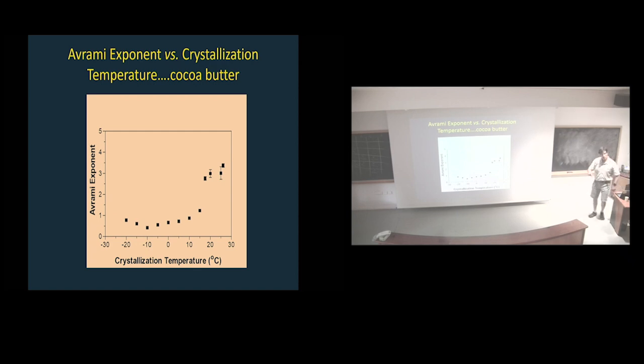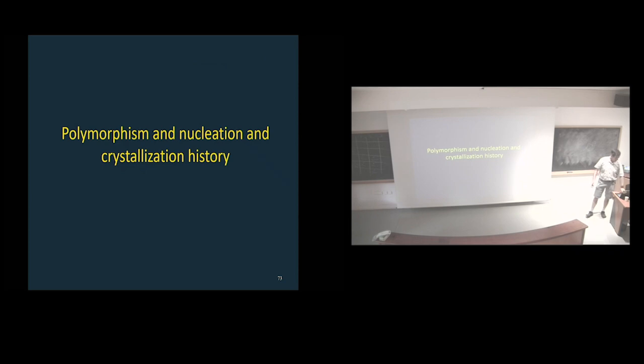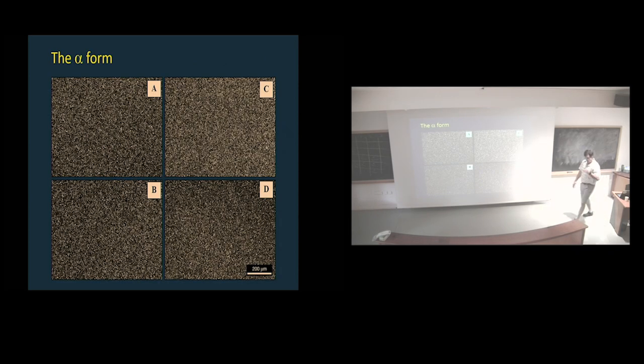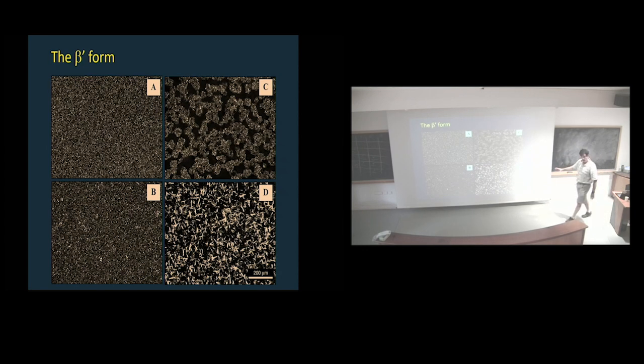And when you look under the microscope, you actually see domains that are gigantic, like 100 microns, and they're balls. They're not balls, but be very careful when people look under the microscope and try to say something about the polymorphism, because these were all crystallized in a certain way that would enhance the formation of the alpha form. I haven't given you the conditions there. Now, all of these have a different temperature history for the beta prime form. So all of these, if you put in the X-ray diffraction unit, you get the 3.8, 4.2, you say it's beta prime. You don't know what that means, but you say it's beta prime.